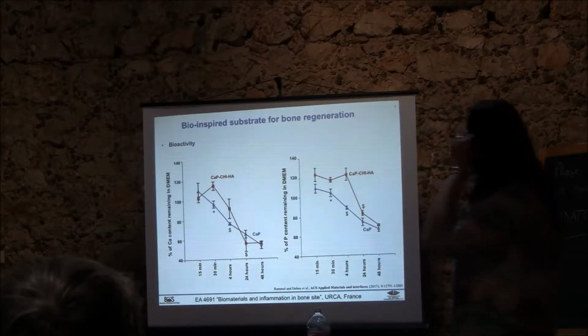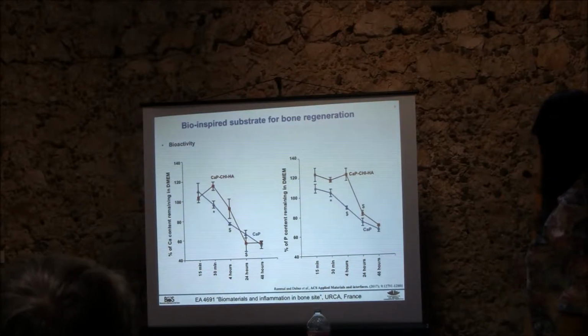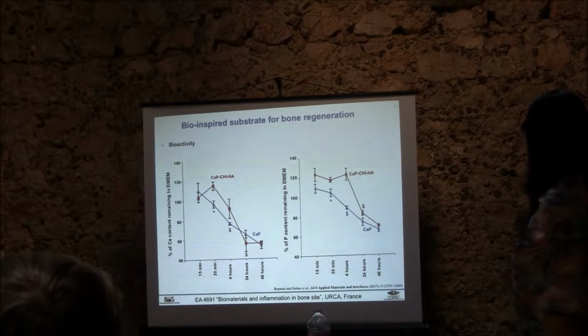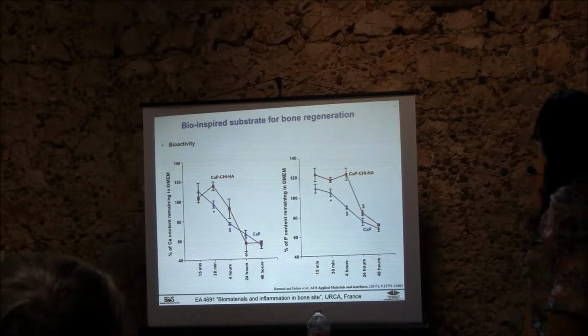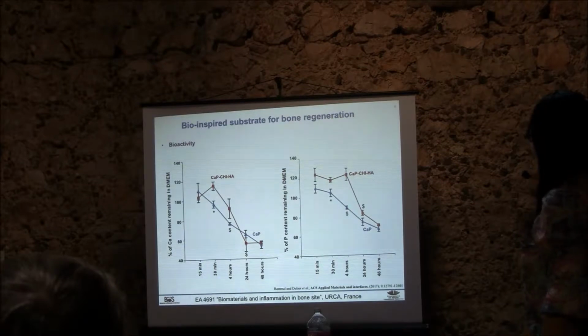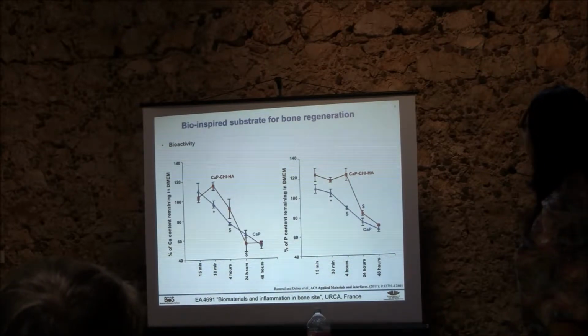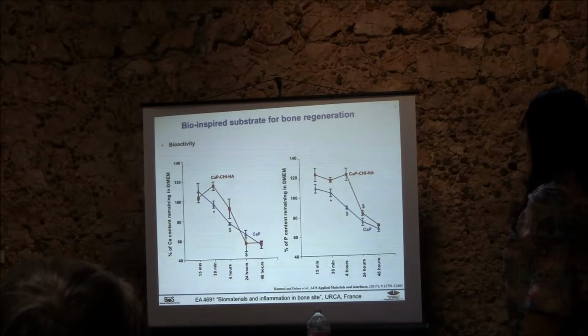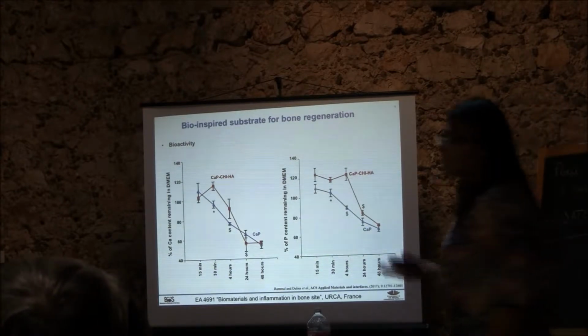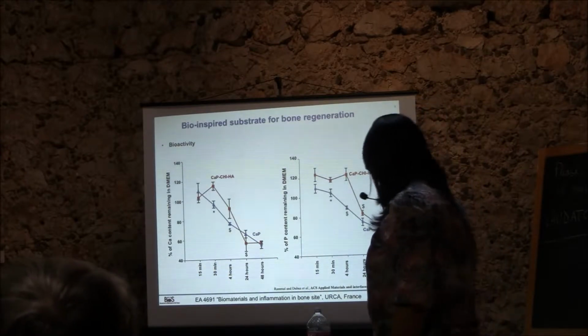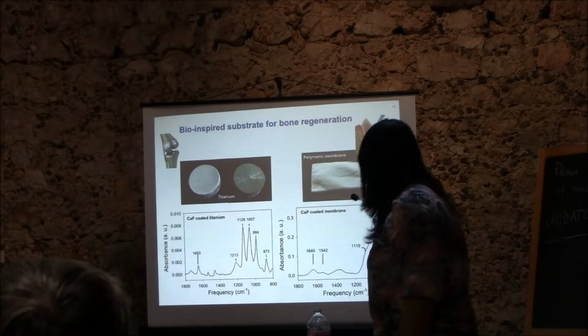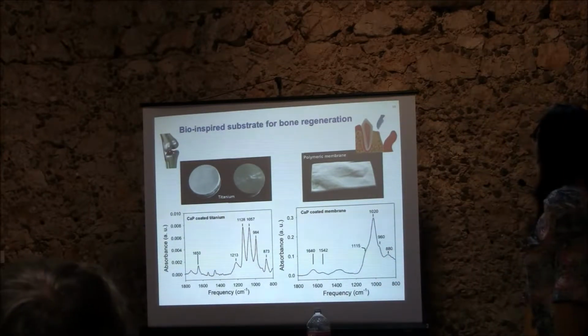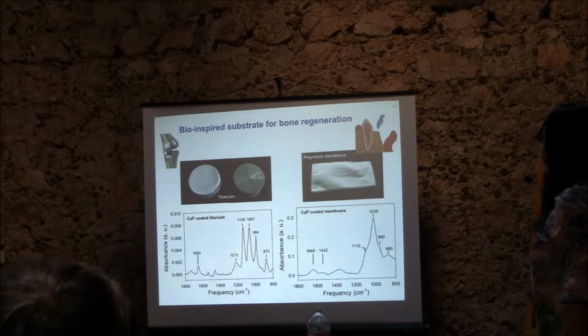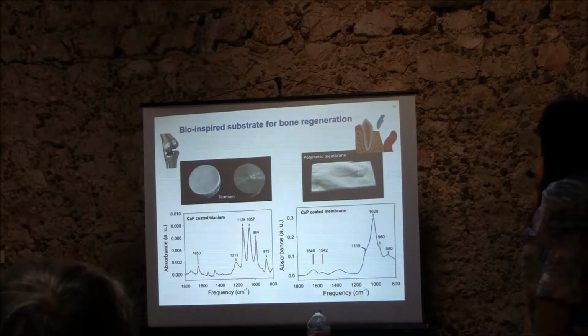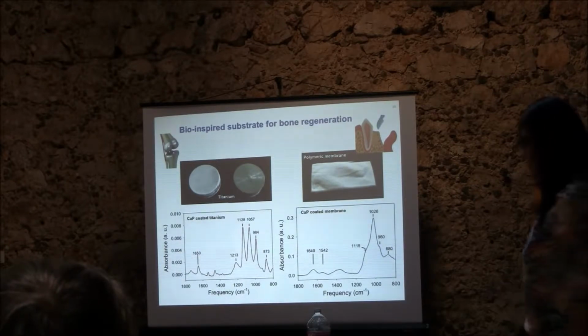Calcium phosphate is a bioactive coating, so we soaked our coating in culture media and measured calcium and phosphorus concentration in the medium. We observed that the addition of polymers into our coating significantly reduced the ion deposition on the surface. Conducted under mild conditions, we built this coating on titanium for orthopedic surgery and on polymeric membrane for dental applications.